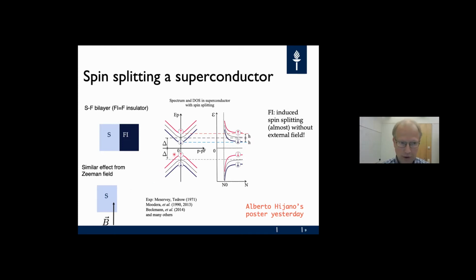What happens in these cases is that the superconducting spectrum splits in spin—there is a spin splitting, and this shows up in the density of states via the spin splitting. The detailed mechanism of how the ferromagnetic insulator splits the spin, and the theory of this for finite thickness superconductors, was presented in Alberto Hijano's poster yesterday.